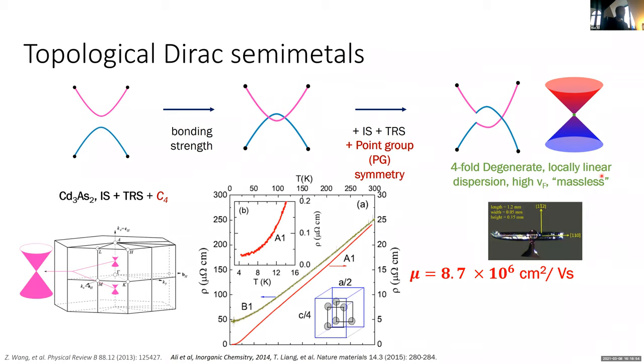And so we saw this a long time ago in cadmium arsenide, where the point group symmetry of choice in that compound was, again, a fourfold rotation axis. And as expected, we saw just crazy high conductivities, with electron mobilities that bordered on 10 million centimeters squared per volt second. So this was actually the crystal that we measured that in, although it's been repeated many times, but the reason I show it is that it's just kind of a rock.